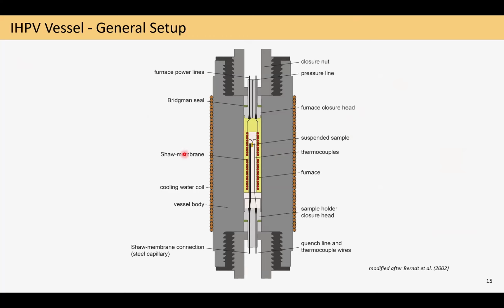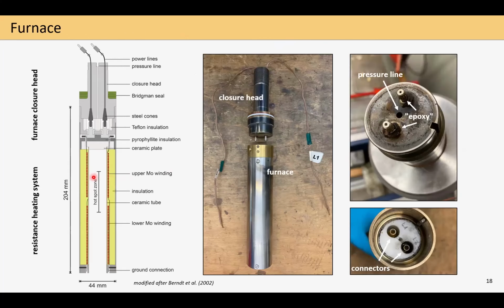And first, one of the main components is, of course, highlighted here in red, the autoclave itself, which in the end represents a quite thick-walled steel cylinder, which has to be very thick to maintain the pressure, and is furthermore surrounded by a cooling water coil to maintain its integrity during an experiment, because inside it's getting hot. Speaking of getting hot, the second main component is the so-called furnace system, which is inserted into the vessel from the upper part. And in detail, the furnace looks like this.